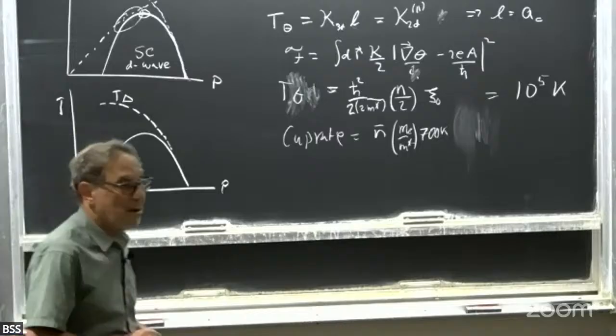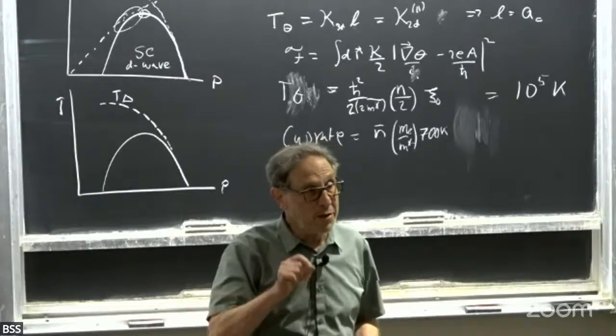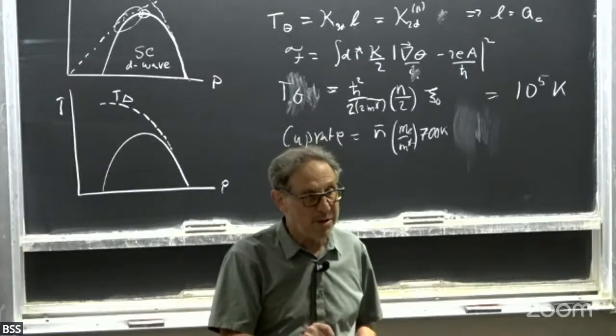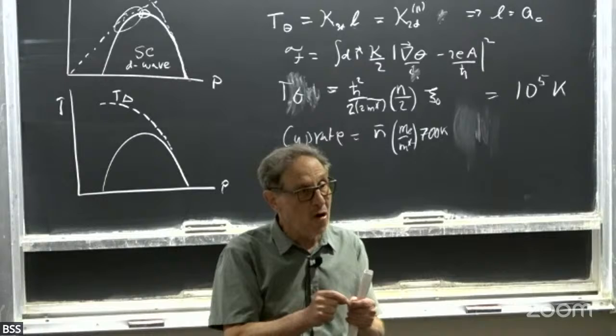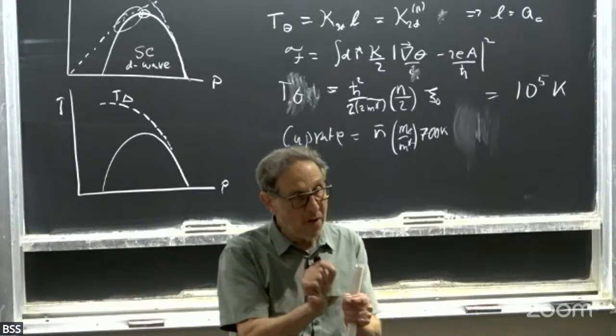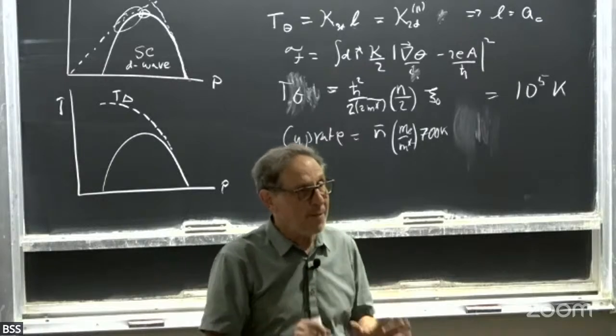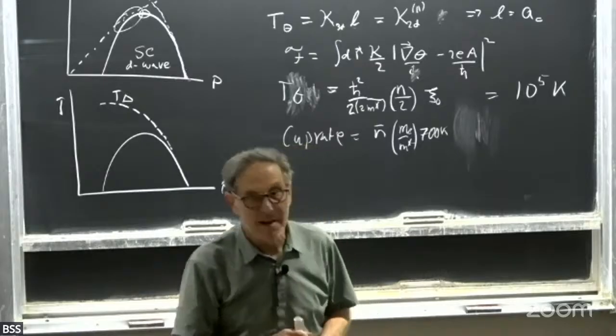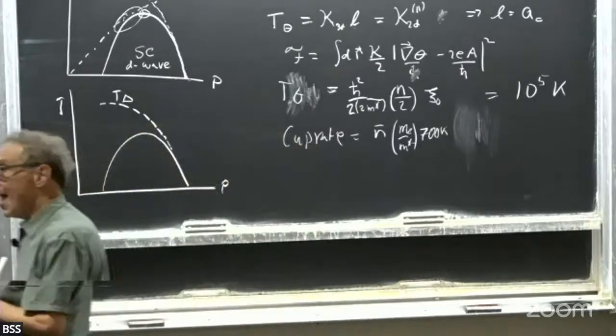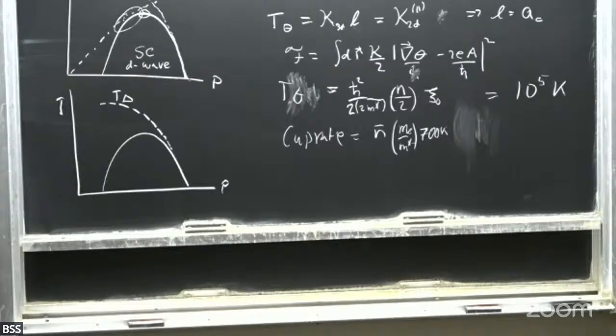No, not the pseudo gap. Again, this is using 0 temperature data or low temperature data, looking at the slope of the gap right near the node, deep in the superconducting state. Okay, so that I don't have to worry about people telling me that it's the pseudo gap and that the gap is something other than superconductivity.